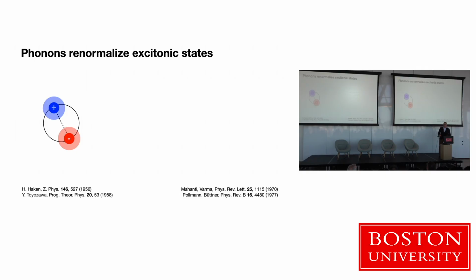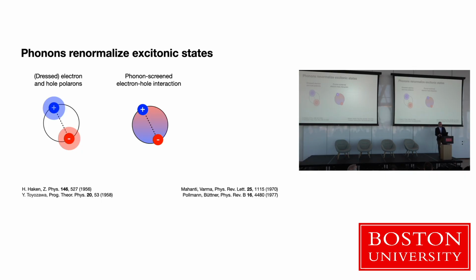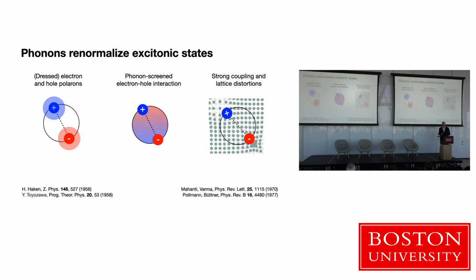So you can imagine that phonons will interact with the electron, they'll interact with the hole, and they'll change the electron and hole energy and the nature of the wave function and such, and that would change how they couple in this exciton. They also, if the lattice vibrations are polar, can screen the electron-hole interaction, so they can actually contribute to the dielectric function, the dielectric constant in the screening environment. And then, if the interaction is strong enough, they can distort the lattice away from its equilibrium positions. So these are three basic ways in which phonons can interact with the exciton.